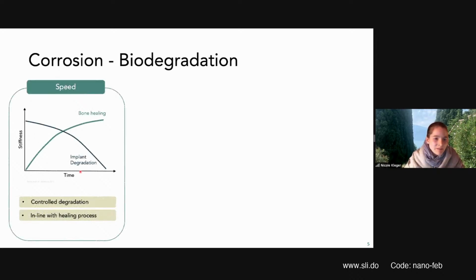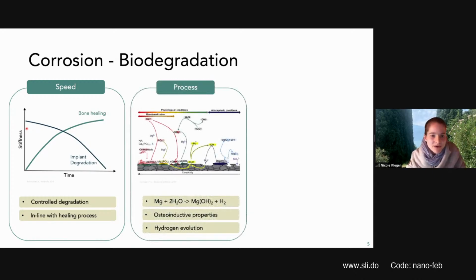Now, for an implant to degrade and to disappear once it has done its job, we need some specific properties. And what we want is that the strength or the stiffness of this implant decreases at a similar rate as the bone healing emergence. So if we think about the degradation going too fast, the bone will not be able to support itself before the implant is gone. And the other way around, if the bone is already healed and the implant stays too long, this will be towards the bioinert materials, which we also don't want. So let's have a look how this process works with magnesium.